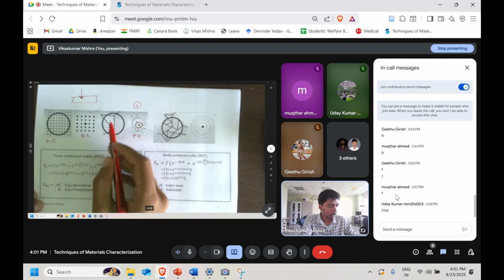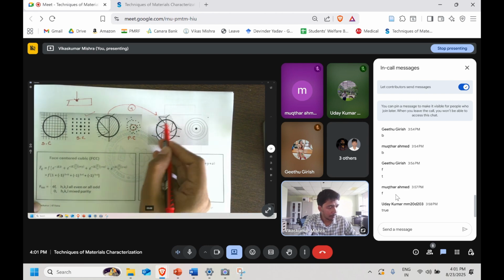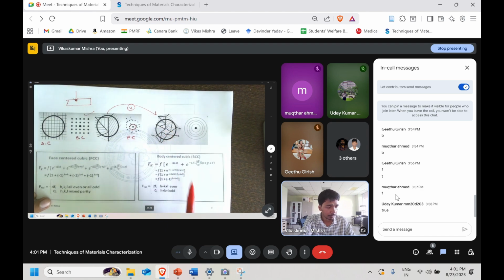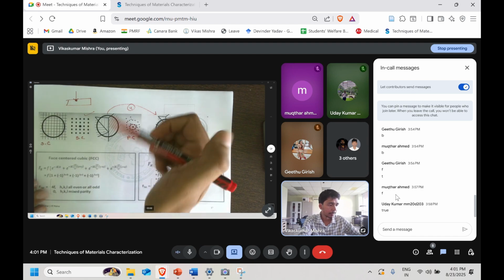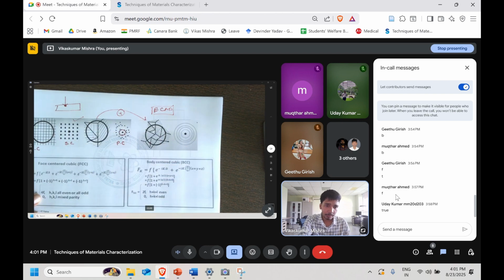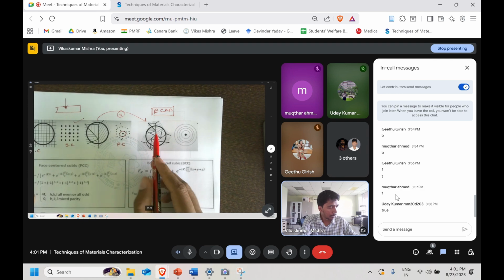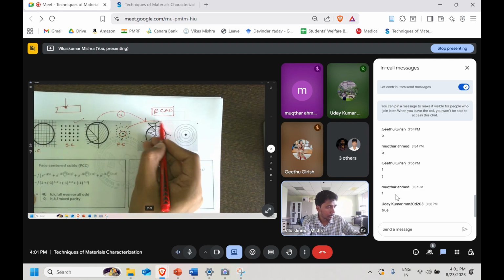Now, instead of 4, in that same area the number of grains has increased. For example, there is a technique, Equal Channel Angular Pressing, ECAP, by which you can deform your specimen. You can increase the number of grains in that. So what will happen? We can see that instead of a spotty pattern, it will become a ring.